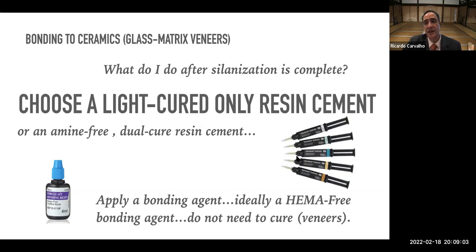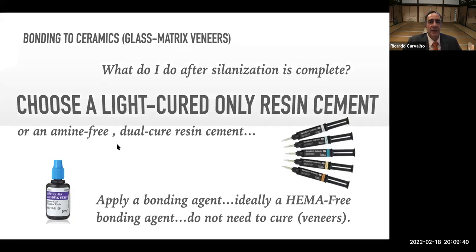And some companies understand that a lot of clinicians have dual cure resin cement in their practice. But the traditional dual cure resin cements always contain amine for the self-curing. And they usually tend to change color over time, and maybe your veneers might get more yellowish. It might be an issue, it might not be an issue, but companies are concerned about that, and they now produce dual cure resin cement which is amine-free, which you then can use for veneers as well, if you are concerned about your cement changing color and compromising your veneer.